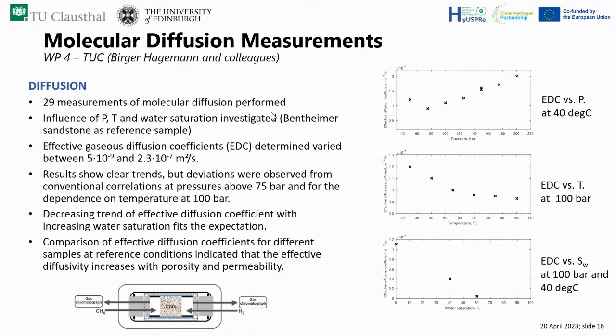So the molecular diffusion coefficients, just very briefly. What was found here, based on 29 measurements, where the influence of pressure, temperature, and water saturation was investigated, is that effective gaseous diffusion coefficients were determined, varying between 5 times 10^-9 and 2.3 times 10^-7 square meter per second. The results show clear trends, but deviations were observed at pressures above 75 bar and for the dependence on temperature at 100 bar. And the decreasing trend of effective diffusion coefficient with increasing water saturation fits the expectation.